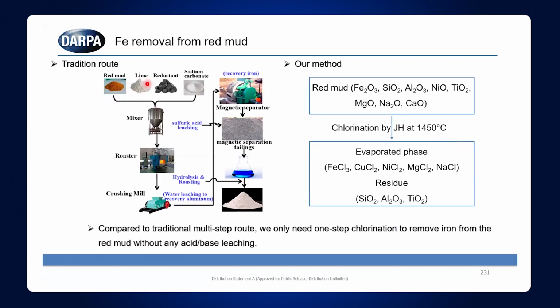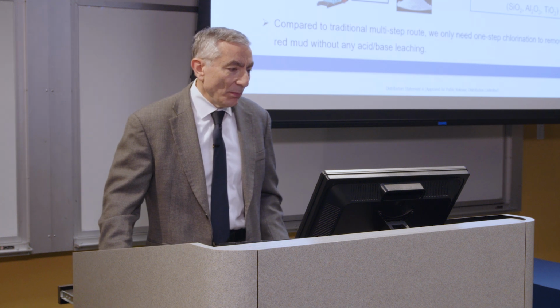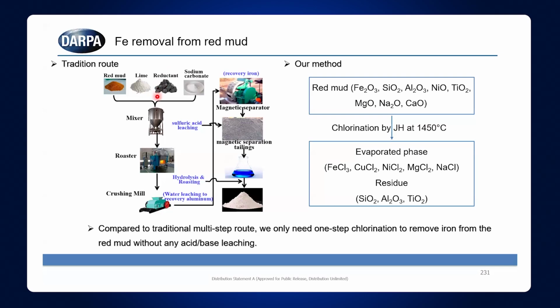Now, how does the industry normally remove the iron from these tailings? Here's what they have to go through. So this is state of the art, this is what's done now: you have this red mud, they mix it with lime, they mix it with a reductant, and they mix it with sodium carbonate. They put it in a mixer, then they roast this. So they put this in an oven, and that's a lot of energy. And then it gets crushed in a mill, and then they do water leaching to recover the aluminum, and they recover the iron with a magnetic separator. And then they go through this hydrolysis step. So all of these steps are buried now in this one step. So you just do the red mud, you do the chlorination reaction. In the evaporated phase, you get this.